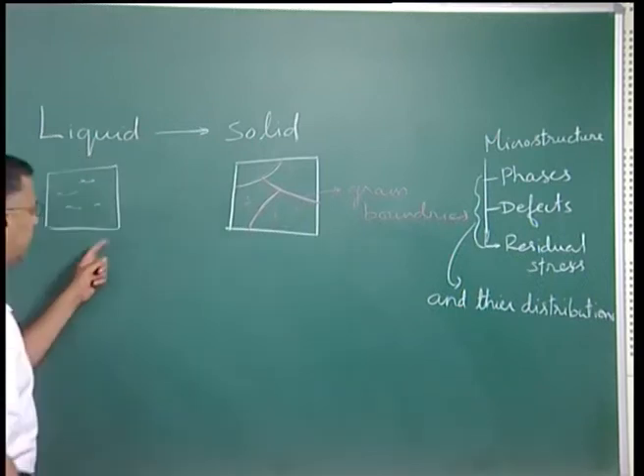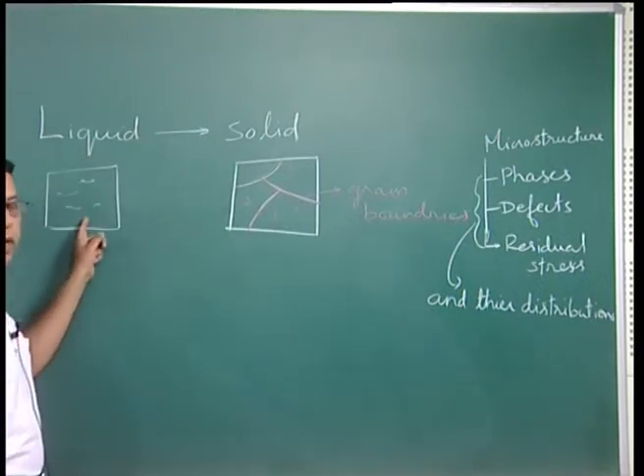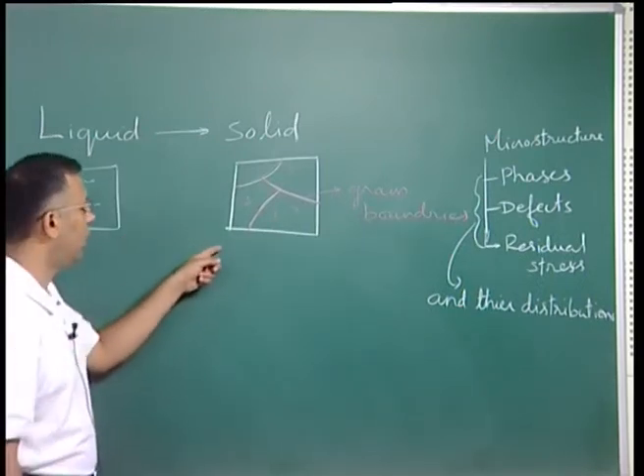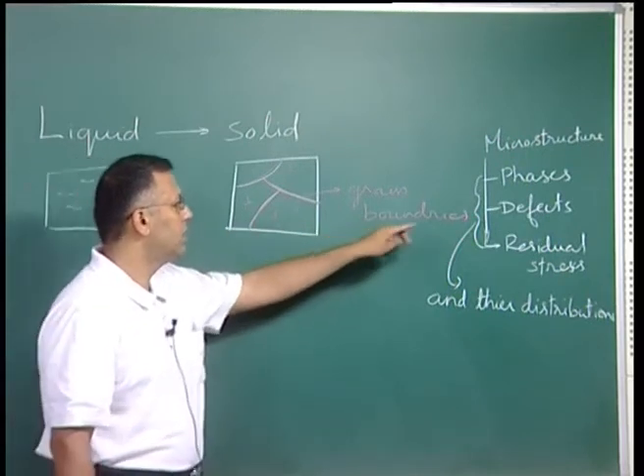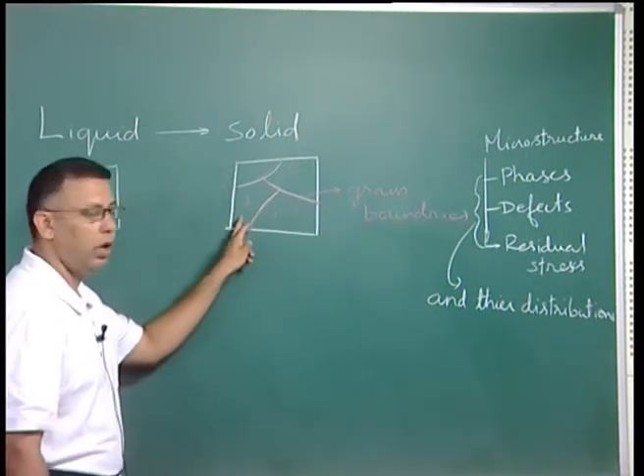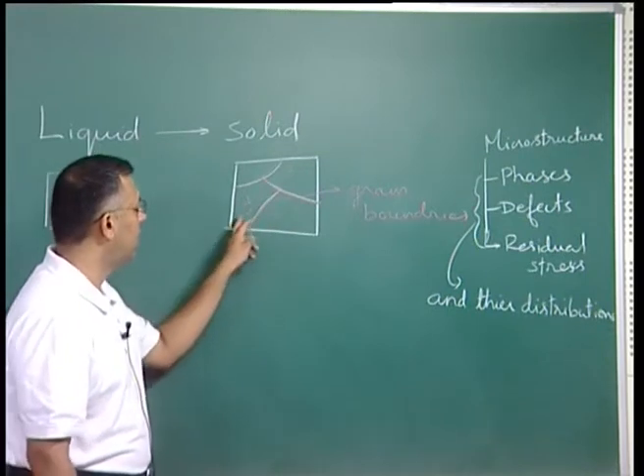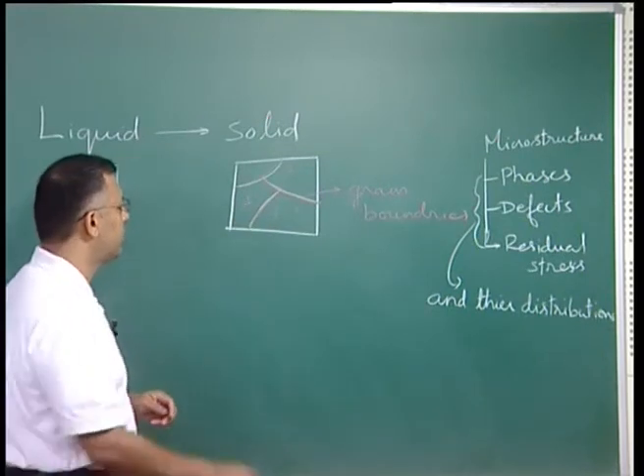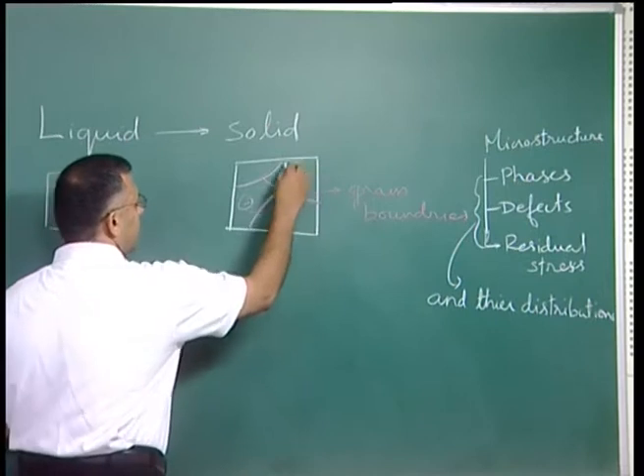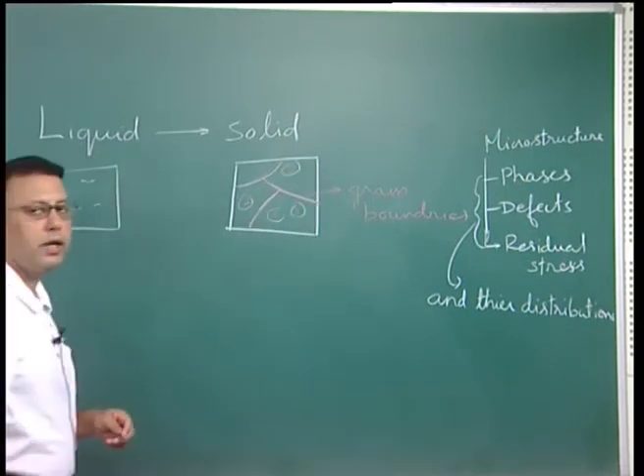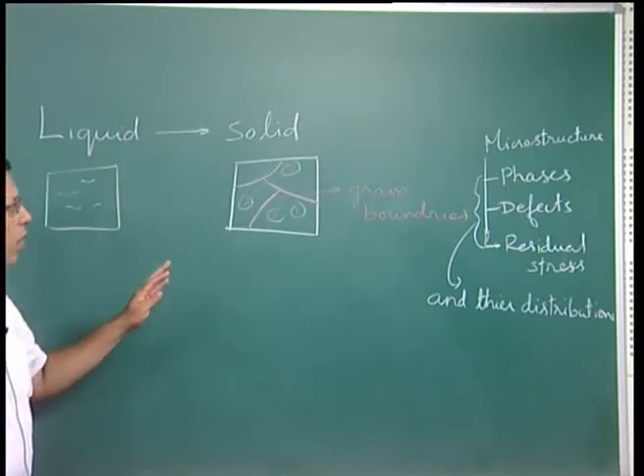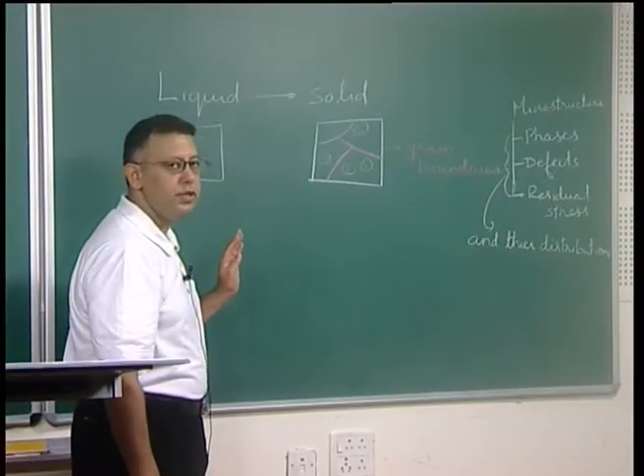So along with this phase transformation, the simplest one we can think of, a pure liquid going to a solid, we have complete change in microstructure. For instance, the solid phase forms, there are defects like grain boundaries and dislocations, and there are stress fields associated with these dislocations. That means all the components of the microstructure change when there is a phase transformation.